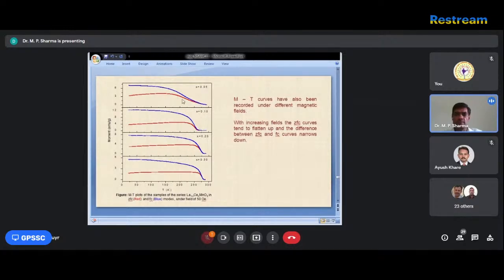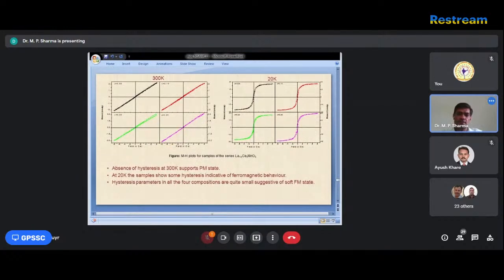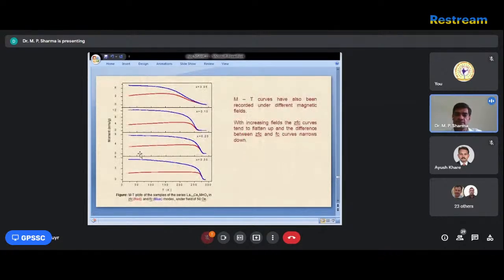Again, the transition point increases. This first one gives nearly 265 around, another one is 280 and another is 285 and so on. So TC tends to increase with Ce content, but only up to nearly 20%. After that it is almost constant. And the ZFC and FC curves depart from each other right from the temperature where the FM state starts, and after that the PM state.